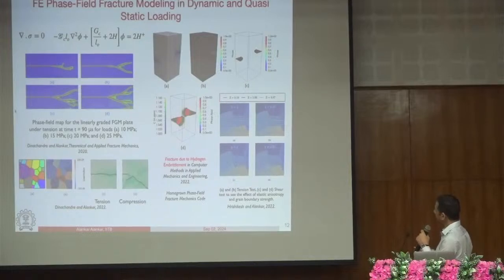Right? Some more simulations where for the first time we introduced that the critical fracture toughness is actually not isotropic, it is anisotropic. That means if you deform a polycrystal, the crack does not always propagate in the horizontal direction if you apply mode 1 type of arrangement. The crack may go up, down, it may show a very different path. That is happening because the crack does not see the fracture toughness of the matrix material as isotropic. Otherwise, the crack always would have propagated horizontally. But in this case, the fracture toughness is anisotropic. That's why wherever there is lowest resistance to crack, it propagates in that direction. This particular simulation took about 30 days, right?